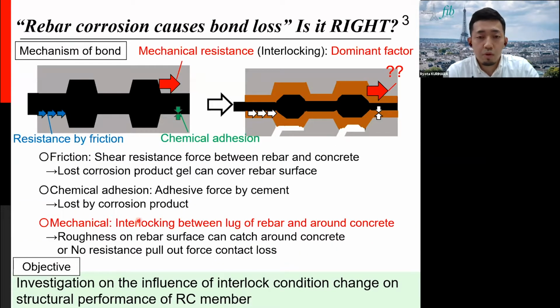So let me organize the components of bond: three factors, mechanical resistance, friction, and chemical adhesion. Of these factors, the mechanical one, by interlocking between the lugs of the rebar and concrete, is dominant. So for achieving a sound bond, the deformed bar is used widely. The friction is the shear force between rebar and concrete, and it is considered that the corrosion product around the rebar surface causes it to be lost by rebar corrosion. And the chemical adhesion is generated by the cement, but it is lost immediately by rebar corrosion.